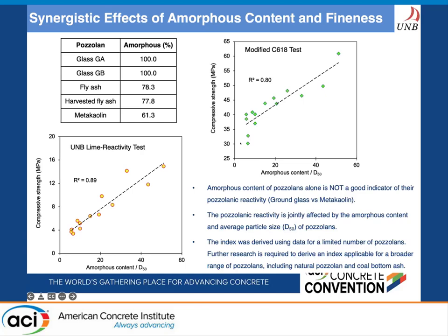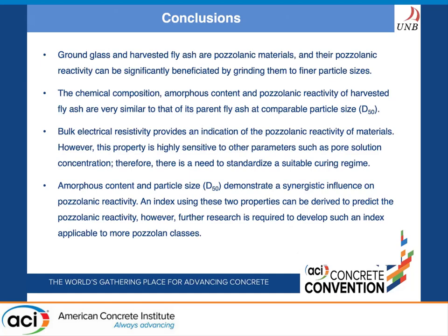In conclusion, ground glass and harvested fly ash are pozzolanic materials whose reactivity is highly dependent on particle size. The amorphous content, chemical composition, and reactivity of harvested fly ash are very similar to parent fly ash when the particle size is similar. Bulk electrical resistivity can provide an indication of reactivity, though this property is highly complex. The amorphous content and particle size of materials can be used together to develop an index to assess reactivity. Thank you.